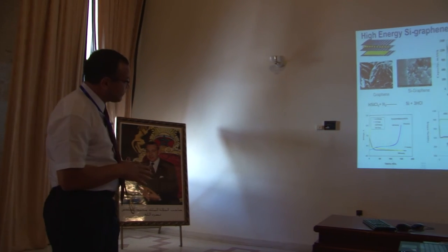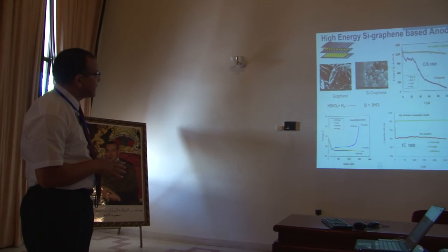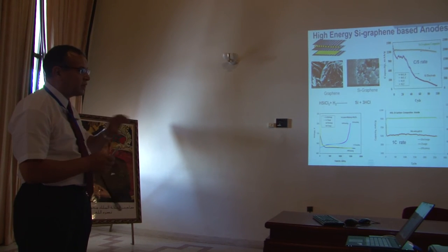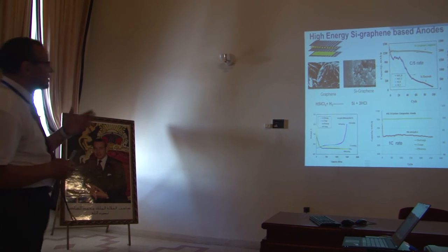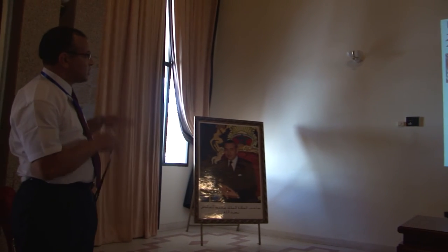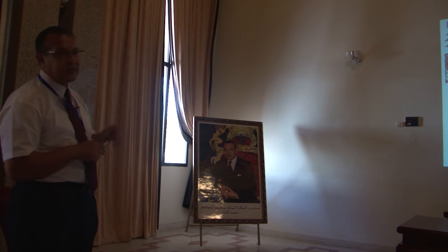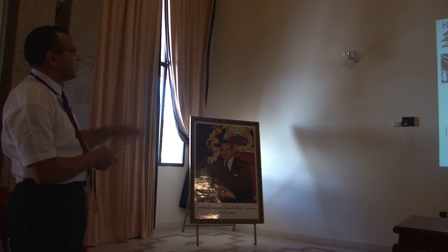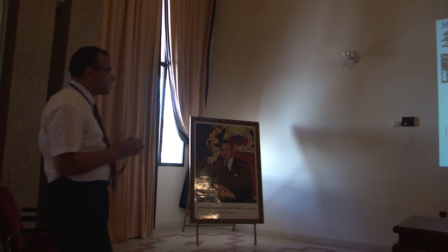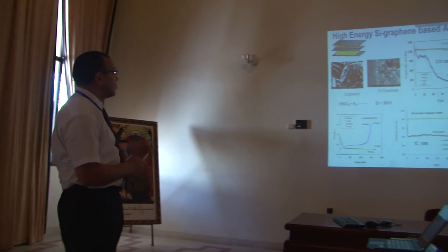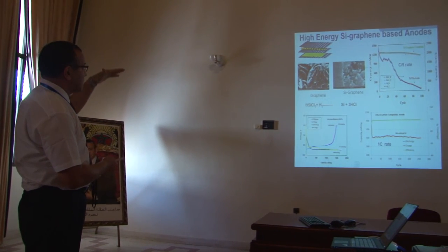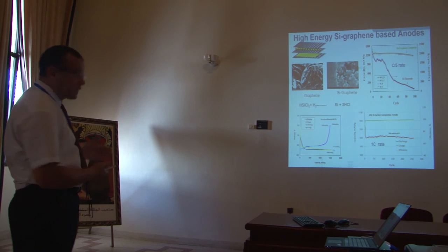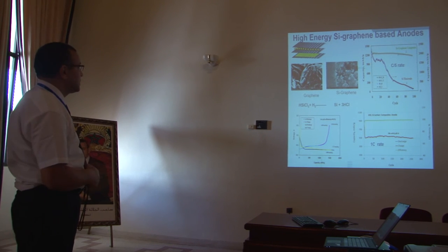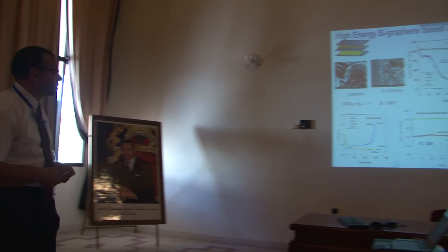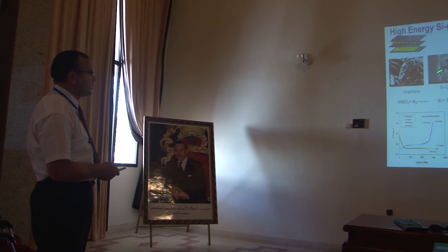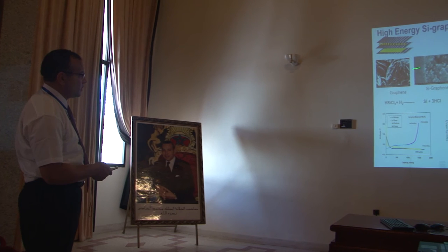Graphene is very flexible. So you're not doing it like in graphite where you're intercalating using an electron transfer. It's basically just accommodating nanoparticles of 20 to 30 nanometers between graphene sheets. The idea is the particles are small, so it takes a long time to crack. Once they crack, the graphene sheet will collapse on them and then keep conductivity. That's the role of the sheet. But they also can act as active material. You can see here, for instance, there are plenty of nanoparticles in the sheet.